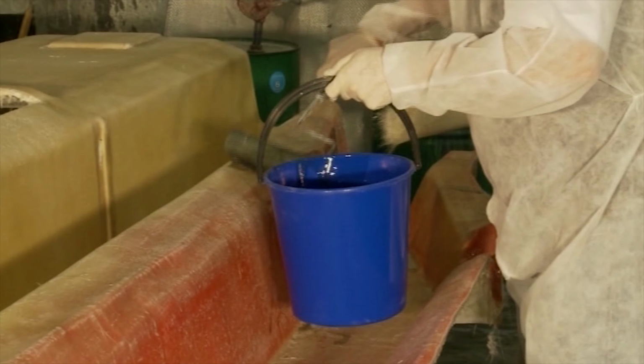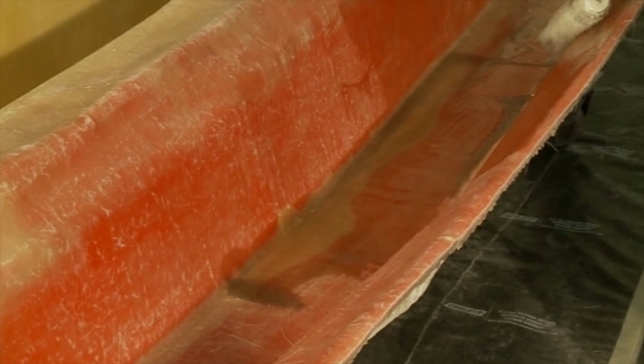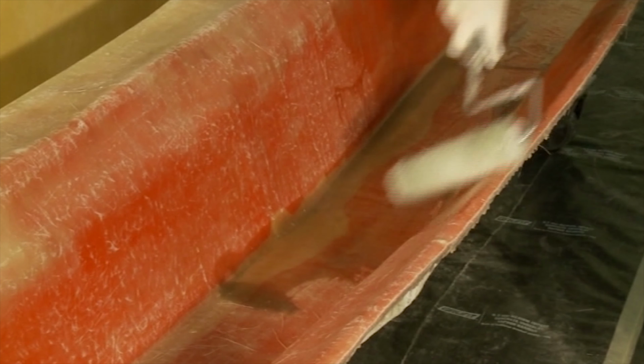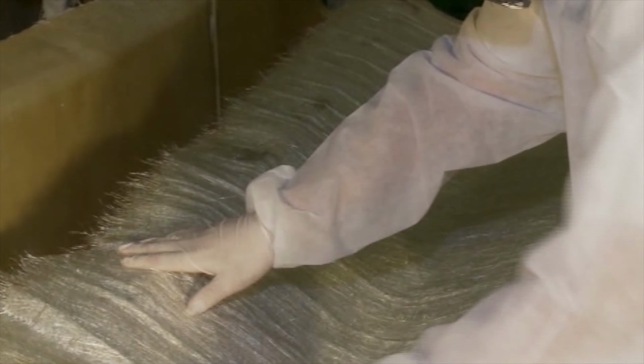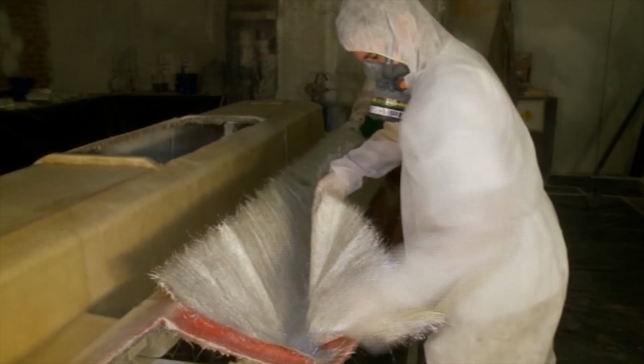Hand laminating involves the use of sheets of fiberglass matting and cloth of uniform weight and thickness combined with expertly chosen resins. These resins are applied to the gel coat surface with lamb's wool rollers or brushes to ensure that the area for fiberglassing has been moistened. This process is called wetting out. The matting is then positioned onto the resin. Once this is completed, air that may have accumulated under the mat is rolled out using thin aluminium rollers. This ensures the strongest laminate for your boat. The process is repeated until the exact strength to weight ratio is achieved.